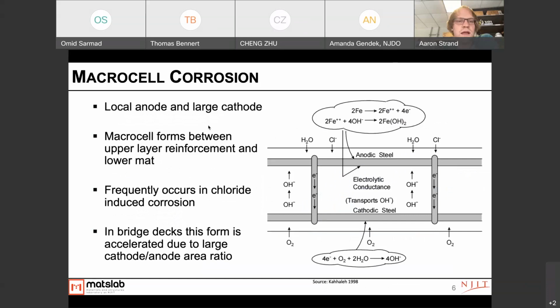What we're looking at is called macrocell corrosion, and this forms between the upper layer reinforcement and the lower mat of reinforcement inside the deck. This forms when there's a local anode and a large cathode. This frequently occurs in chloride-induced corrosion as the chlorides reach the top anodic steel. In bridge decks, this is accelerated due to the large cathode to anode area between the reinforcement bars within the bridge deck.